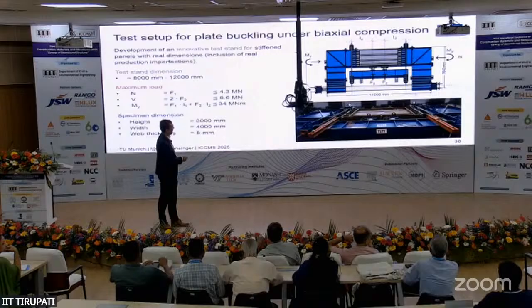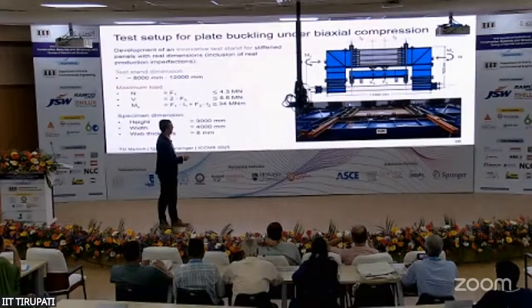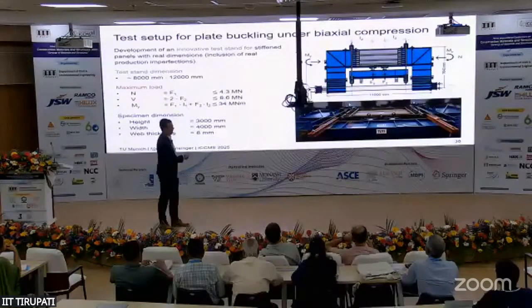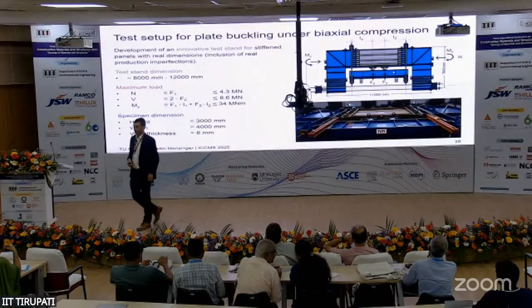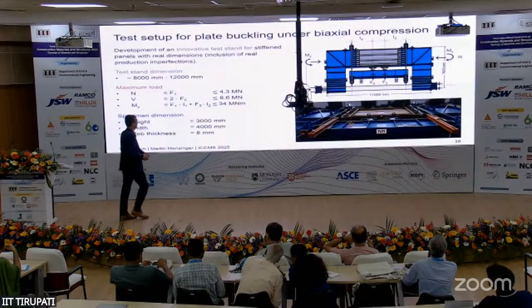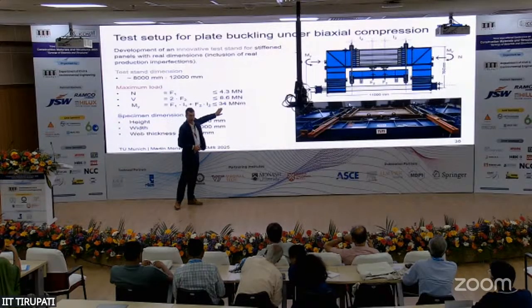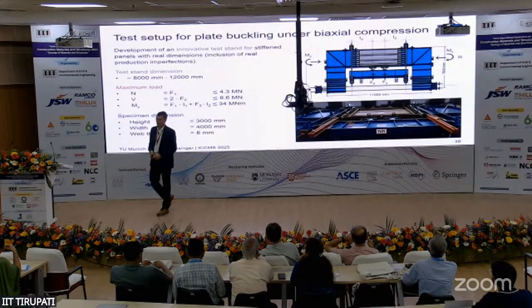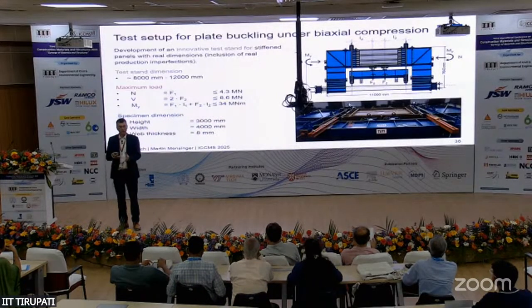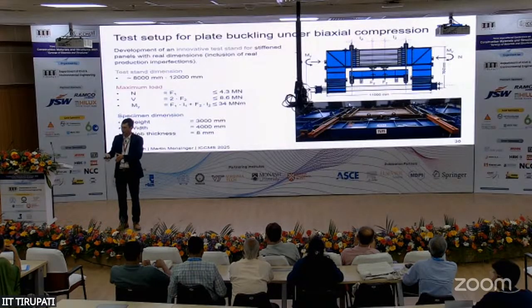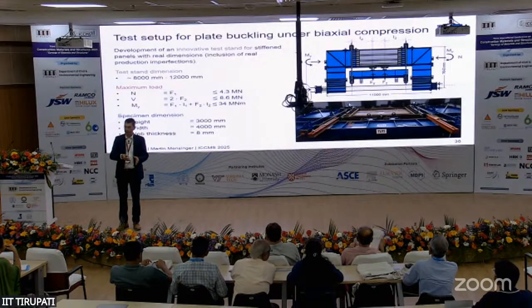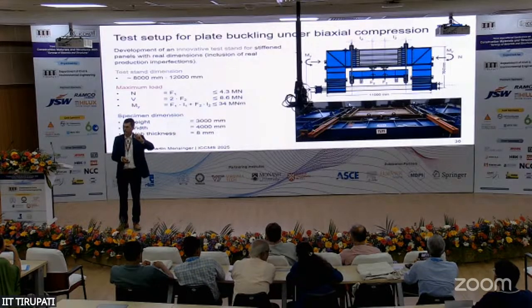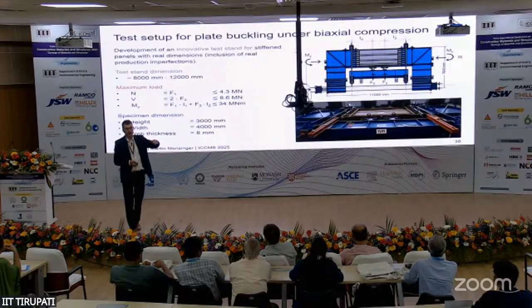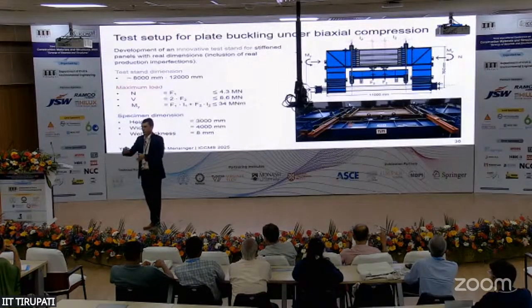which has a span of 11 meters, 7.5 meters high. This is high-strength steel. Also, the blue parts are high-strength steel. And we were able to perform tests on web panels with a size of 4 by 3 meters. And we were able to apply a bending moment of 34 meganewton meters and a cross-direction load of 8.6 meganewton. So we are not in the range of the real bridge, but we are pretty close to those web panels, which is essential if we want to consider especially weld imperfections in the right way. Because if we choose the web panel too thin, we will have different web deformation and imperfections due to welding than in realistic structures.